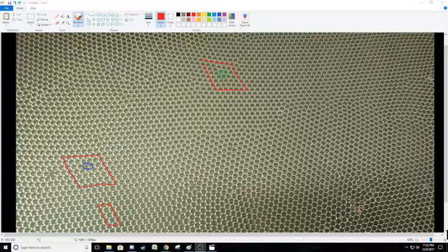However, if we go up here to this green circle where we have a dislocation, you see that the same no longer holds true. If we draw 7 to the right, 7 down, 7 to the left, and 7 up, you see we don't actually fully connect. We don't close our circuit. And you can see this gap here, this distance of one bubble in this direction.